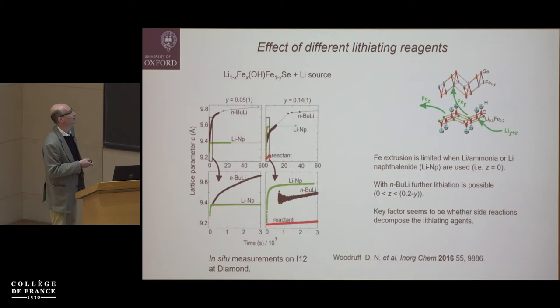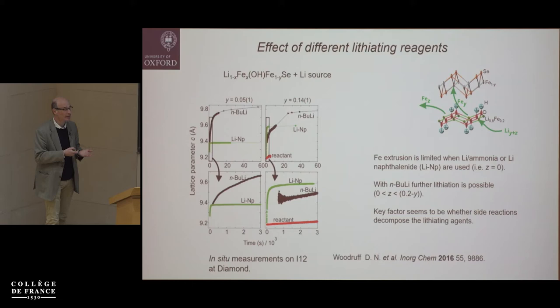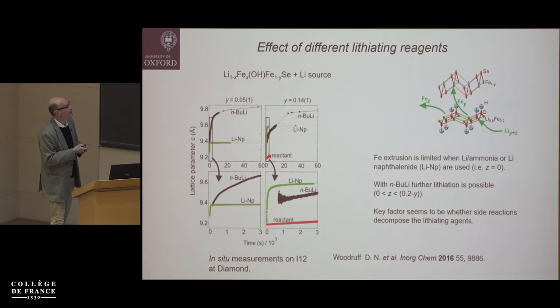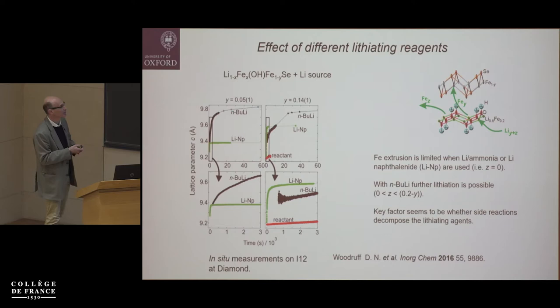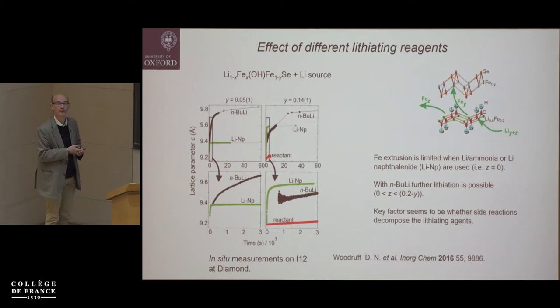We're inserting lithium into the selenide layer, but we're not changing the total amount of iron in the compound — the lithium enters the hydroxide layer and displaces the ~20% of iron that was there, which moves to fill vacancies. We make a pristine iron selenide layer and introduce electrons by inserting lithium atoms from the lithium-ammonia solution — a reductive intercalation that simultaneously makes a stoichiometric iron selenide layer. The iron absorption edge shifts to lower energy, consistent with iron reduction.